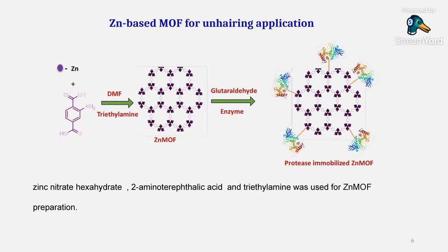Here, what we did is we took zinc salt. Why don't we take any other metal? Zinc is a very important metal, biologically relevant also. And we took 2-amino terephthalic acid as the organic moiety, and we formed the metal organic framework, and we used glutaraldehyde as a cross-linker. Glutaraldehyde has a dialdehyde group; one end will attack the NH2 group of the amino terephthalic acid, and the other side can be linked with the enzyme. So the protease-immobilized zinc MOF will be like this.